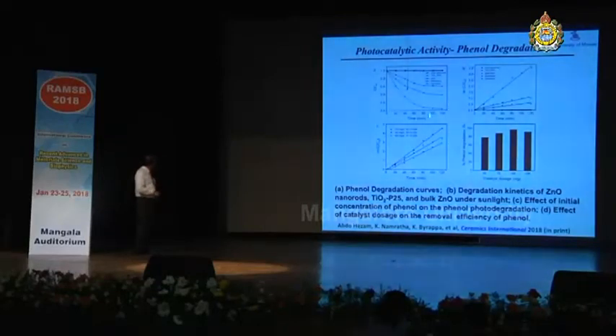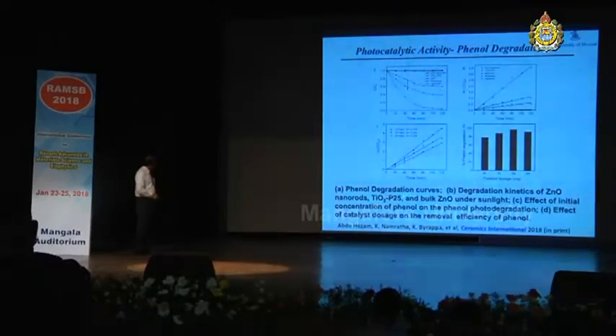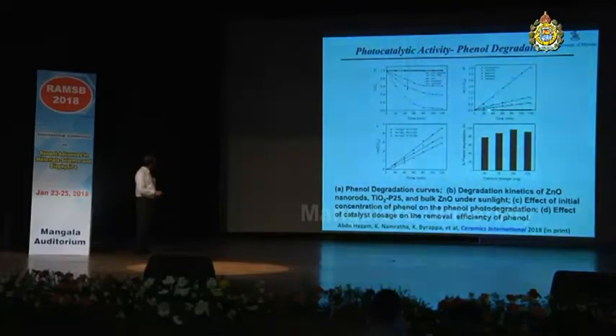And the phenol degradation curves are shown here, and the degradation kinetics of the zinc oxide nanorods, and also the commercially available titania, and the bulk zinc oxide. This is under sunlight, and the effect of the initial concentration of phenol on the degradation. And here this shows the effect of catalyst dosage on the removal efficiency or degradation of the phenol.